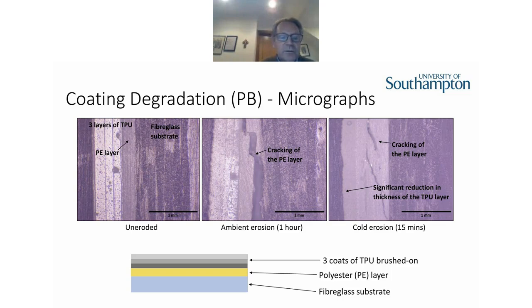So the things to note, obviously you can compare the uneroded to the ambient. The one thing that is quite evident is the cracking, or it looks like you've got some delamination between the polyester and possibly the TPU layers, and some failure within the polyethylene itself, even at ambient temperatures. So that is a concern. Whatever erosion's doing, it's starting to disbond the 3 layers of polyurethane. If you get colder, you also get cracks in the polyurethane system.